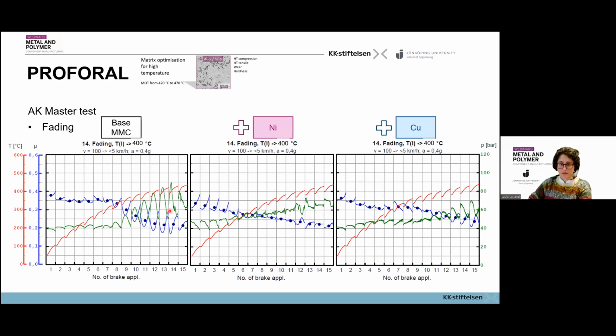You see here that the green curve is pressure. So here we have much variation in the pressure requirements to get a braking performance. With the two experimental materials instead, this width is very much reduced. So by the end of the test, at the same temperature, the coefficient of friction is slightly higher and less pressure is required to get it. These were the lines for the comparison in terms of pressure and coefficient of friction.